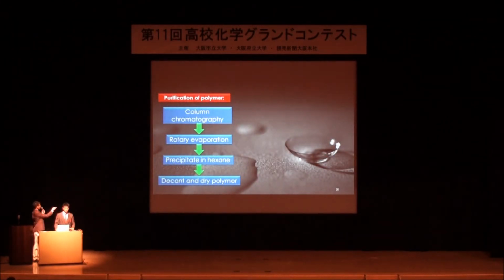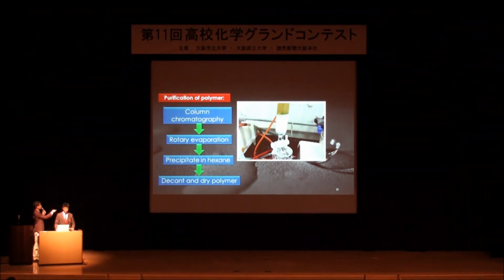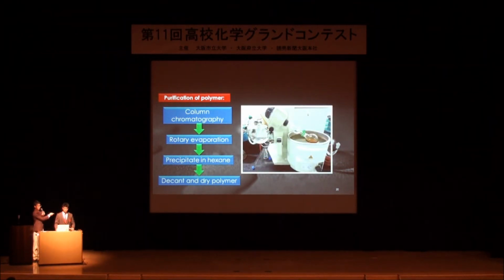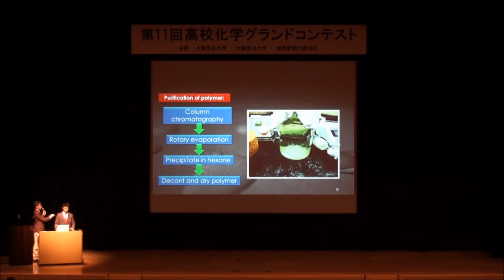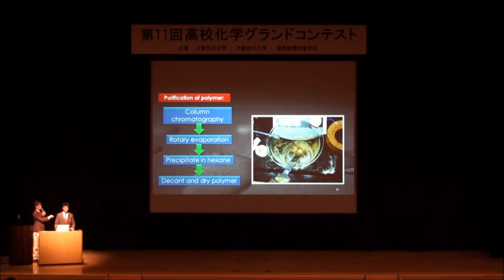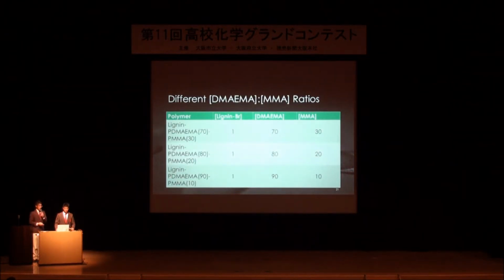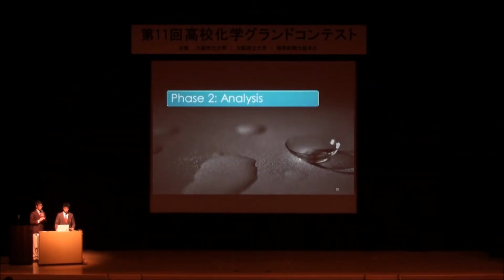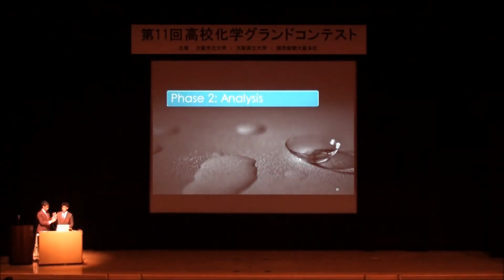First, we'll perform column chromatography to remove impurities. Second, rotary evaporation to remove excess solvent, followed by precipitation in hexane to obtain our polymer. And finally, we will dry and decant our polymer. We have synthesized 3 types of polymer so far, using different ratios of DMA-EMA to MMA. Now I'll pass the time back to Brent for phases 2 and 3.